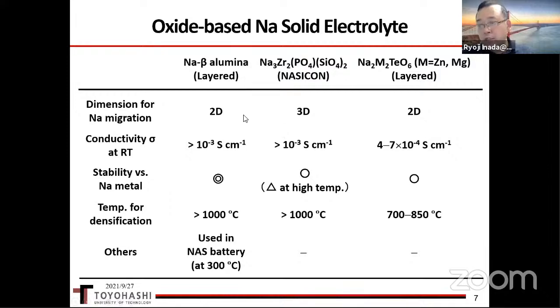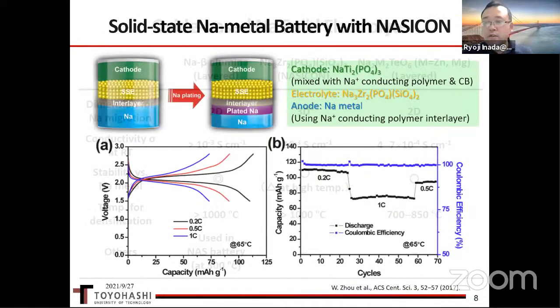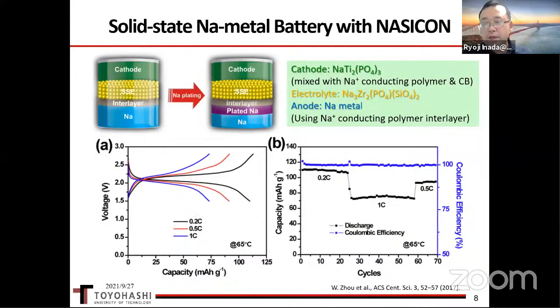And the layered type material was reported in 2010. This material has lower processing temperatures compared to the other two old solid electrolyte materials, sodium beta alumina and NASICON. Using a NASICON electrolyte, a solid-state sodium metal battery operating at a lower temperature was fabricated successfully. This was reported in 2017. The cathode is sodium titanium phosphate mixed with a sodium conducting polymer and carbon black. The electrolyte is NASICON, and the anode is sodium metal, but between the NASICON solid electrolyte and the sodium metal, a sodium-ion conducting polymer interlayer is inserted to form a good interface between the solid electrolyte and the sodium metal.